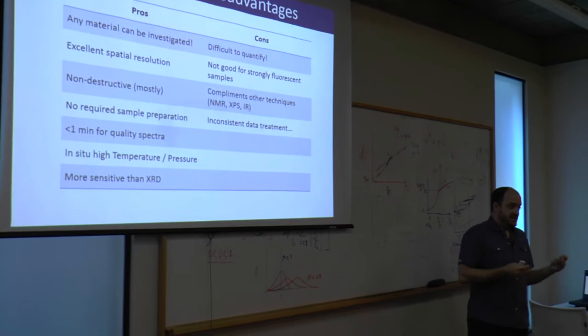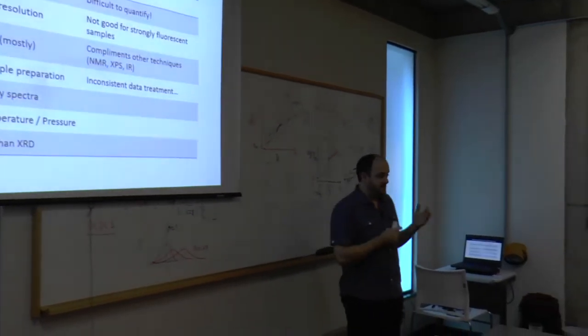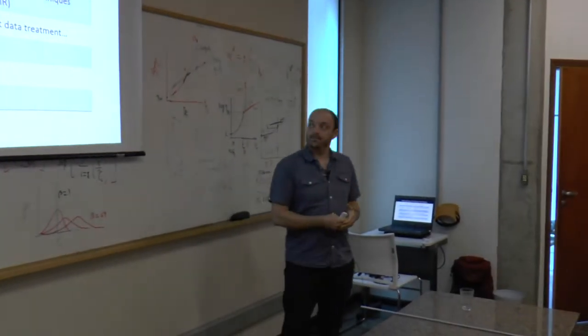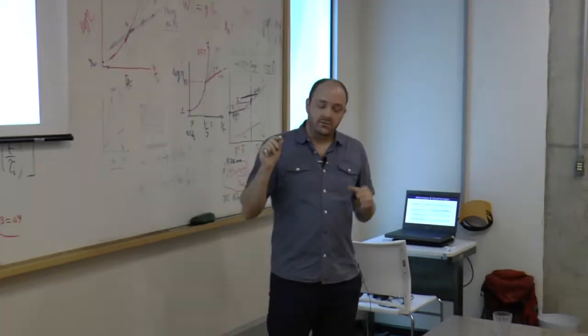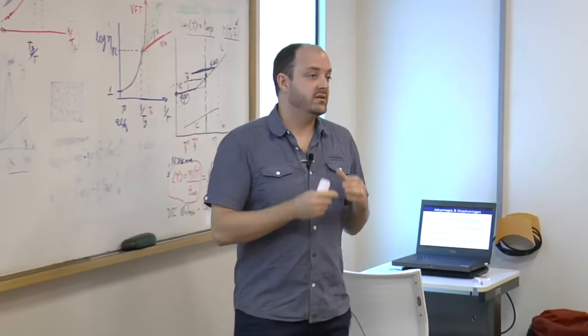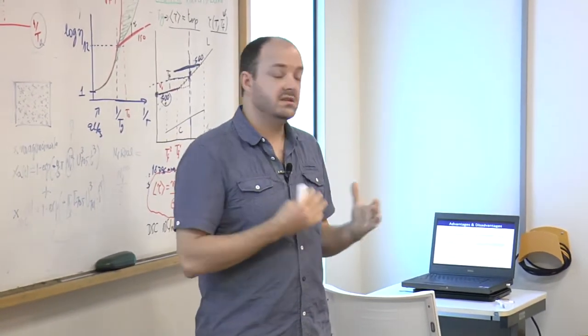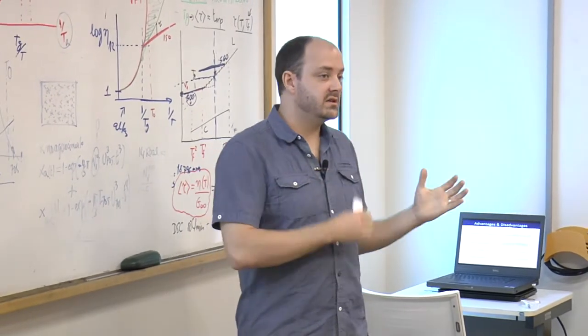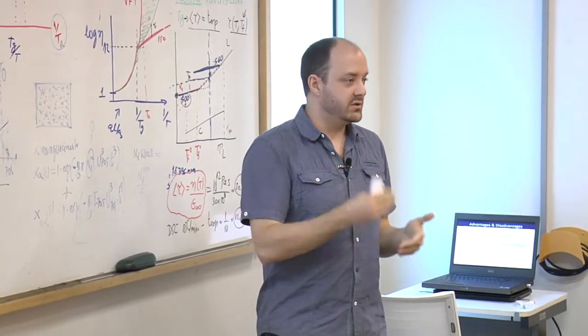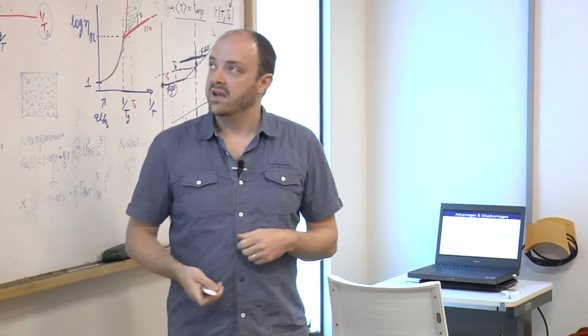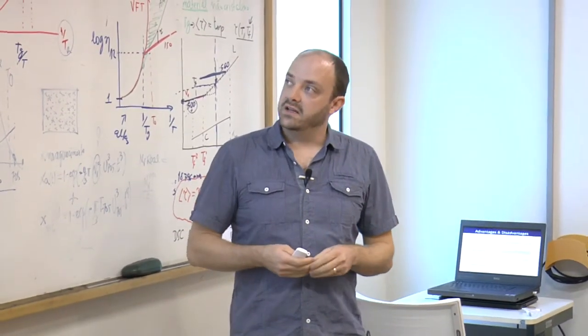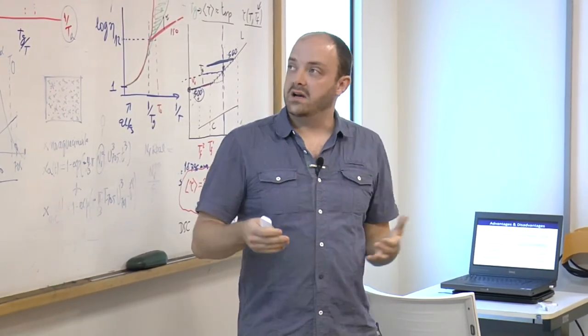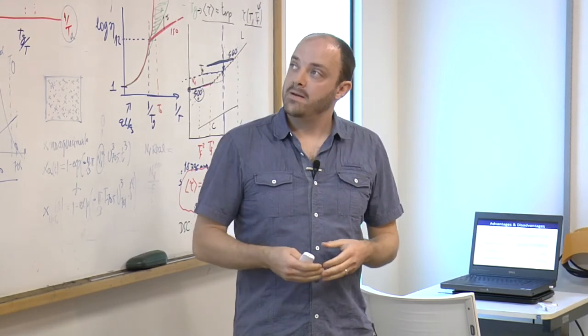The difficulties, as you've seen, is that sometimes and many times it's difficult to quantify. So you really need to have a model that you're testing, and I showed you the example of collecting the bridging and non-bridging oxygens to test whether your QN speciations make sense. It's very complementary to other techniques and provides often different information from them.